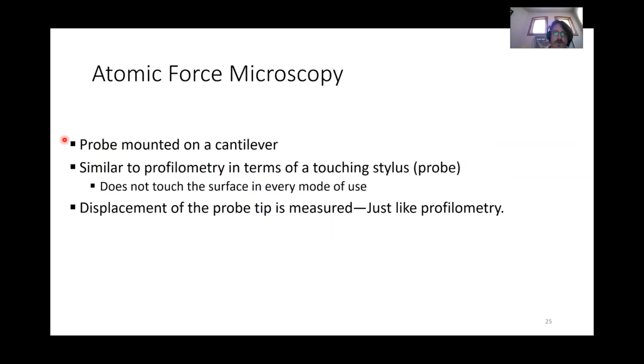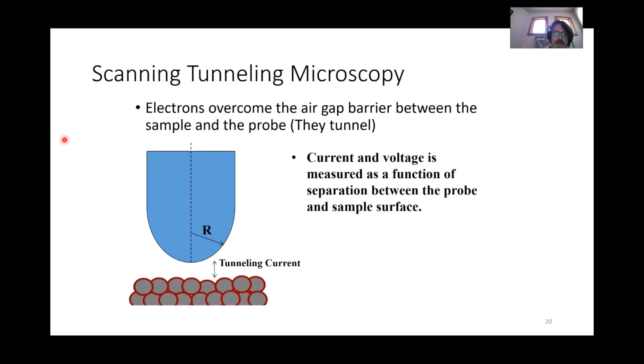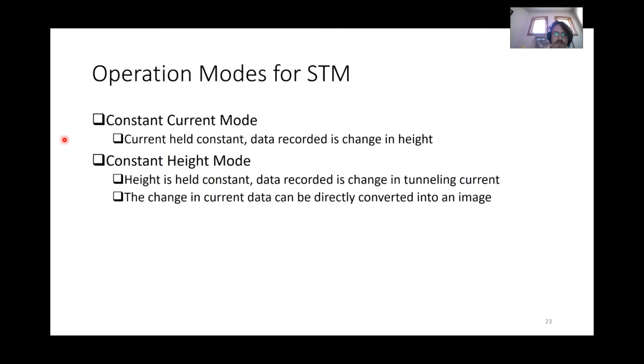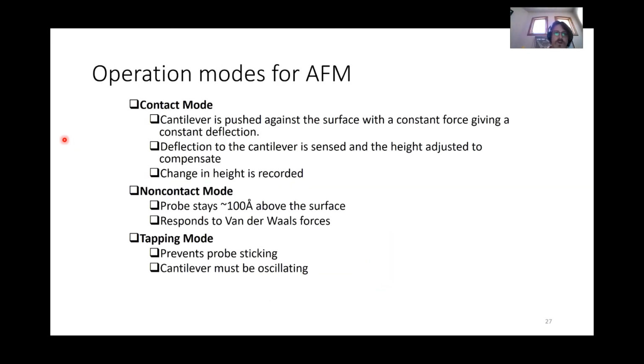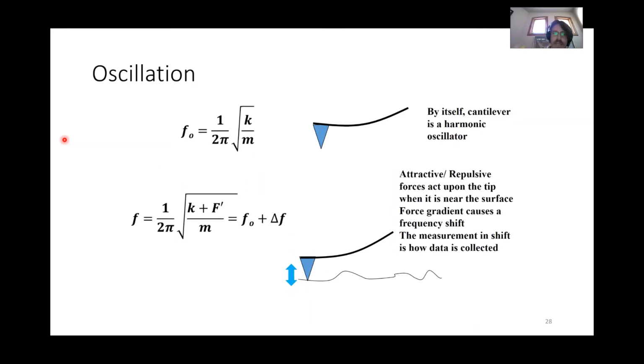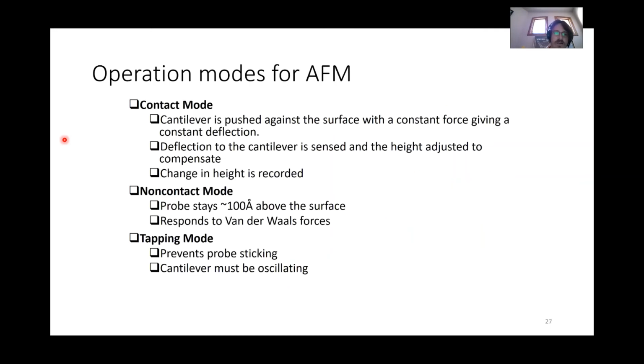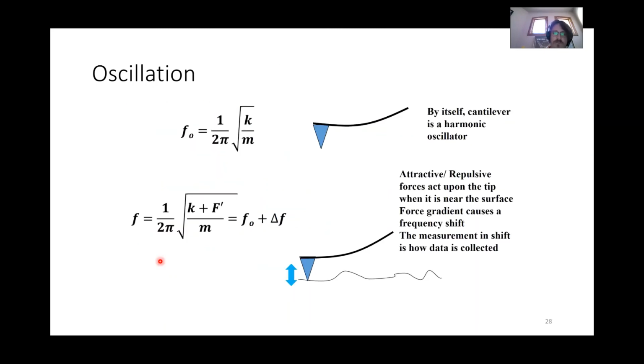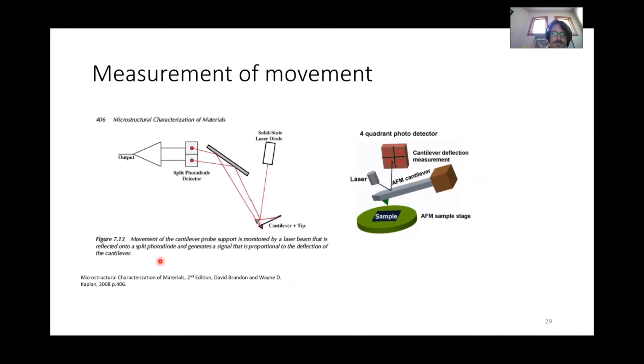So again, it differs from STM, where you're measuring purely a difference in current. Here, when you're oscillating your cantilever, it's a shift in the frequency of the oscillation that gives the data. So I probably should have put here that in tapping mode, you're actually measuring a frequency shift difference to figure out how high everything is.